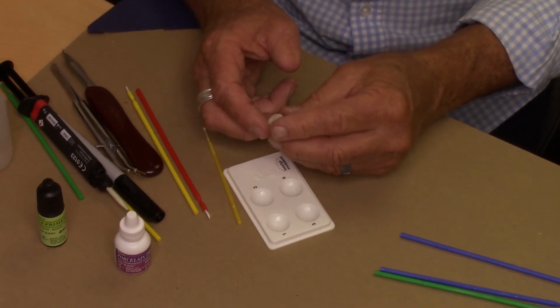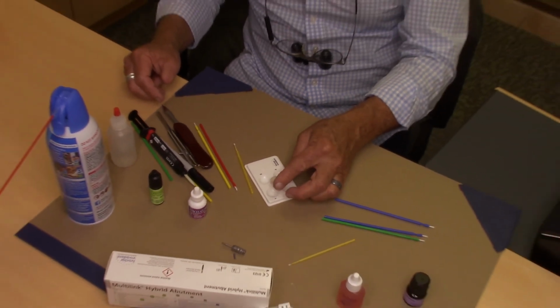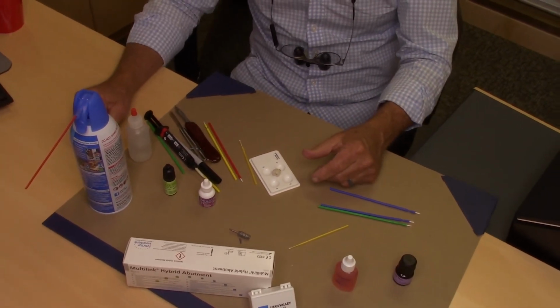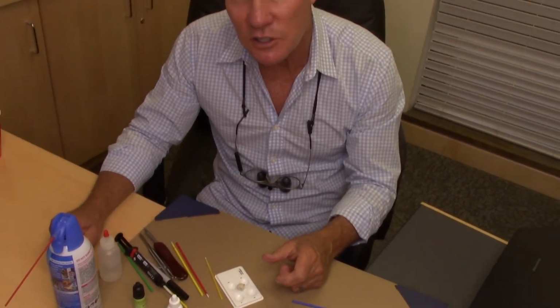Now, as far as bond strengths, Ivoclar in their dental laboratory have actually found that at 15 minutes, and that's your set time with us, you get about 35 to 40 megapascals. So we do get a bond. At 24 hours, they got over 45 megapascals. So the laboratory, obviously, this is going to sit for at least 24 hours before we send it to you.